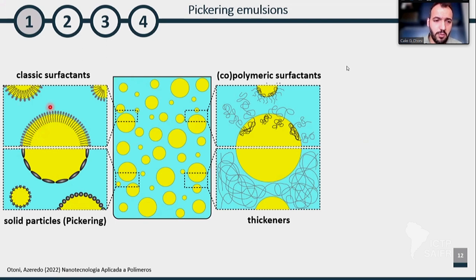So as you know, emulsions are multi-phase systems of non-miscible species, and they are not in thermodynamic equilibrium. If the droplets are small, they can be made kinetically stable, so metastable. And for this, we use block copolymers or even polymers as thickeners to increase the viscosity of the continuous medium and reduce droplet collision and coalescence. But of course, there are the classical surfactants, but I'm talking about polymers here. There are also the particles that sit in the interface, and they create a real shell of structures that prevent droplets from seeing each other and from coalescing.